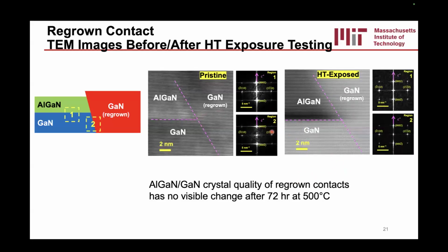The TEM images here are different mostly because the tools are different, but we can see that both in real space and in k-space, the crystal quality is basically perfect. We can't see any cracks or dislocations that have been formed due to this 500C anneal, at least for the regrown contact structures.